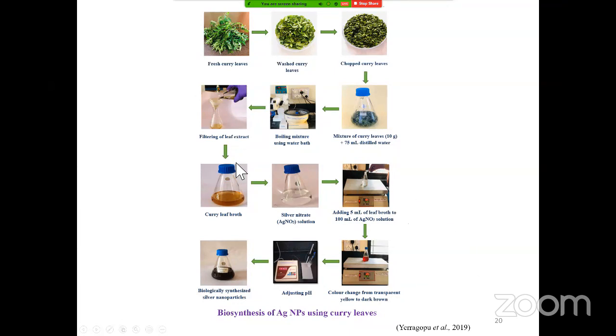This is also a part of my PhD research. I have taken curry leaves because they are high in carbazoles and terpenoids, and have potent antioxidants and heterocyclic compounds, which help in the reduction of metal nanoparticles to a smaller size compared to other plant extracts. So 10 gram of curry leaf has been mixed in 75 ml of distilled water, kept in a boiling mixture using a water bath, and the leaf extract collected.